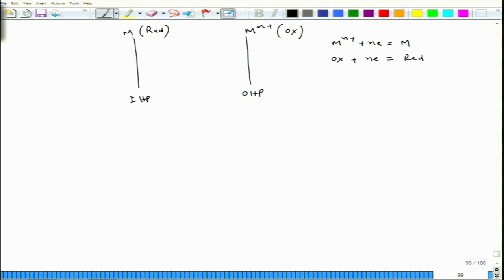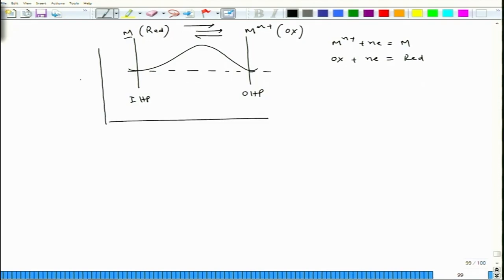And when this metal goes to metal ion or metal ion goes to metal, they would not go straight away like this. Since it is a thermally activated process, they will go over an energy barrier. And they are on the same value. If we consider G, free energy with distance, they will be on the same plane when I equal to I 0. Why? Because if I consider the forward rate and backward rate, let us say this is my forward and this is my backward.